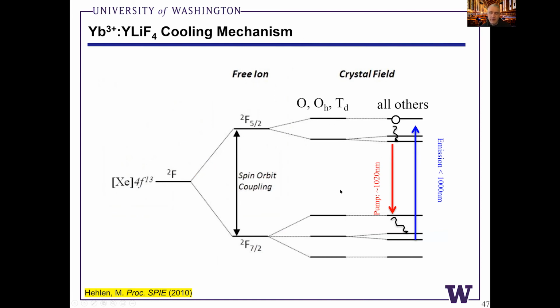Just to give a little more physical insight into what's happening here, the ytterbium 3+ ion is substitutionally doped in the ceramic crystal. This is an f13 system, and spin orbit coupling offsets a doublet 2F7/2 ground state level from a doublet 2F5/2 manifold. And then crystal field splitting can modify the f orbitals of the ytterbium ion a bit further, depending on the point group symmetry of the ceramic.